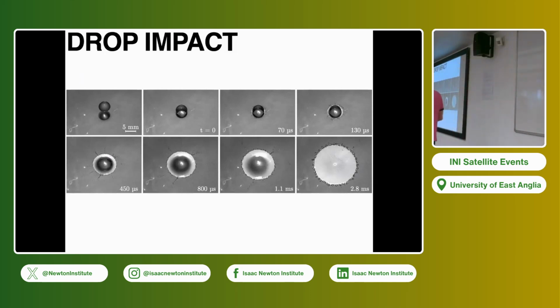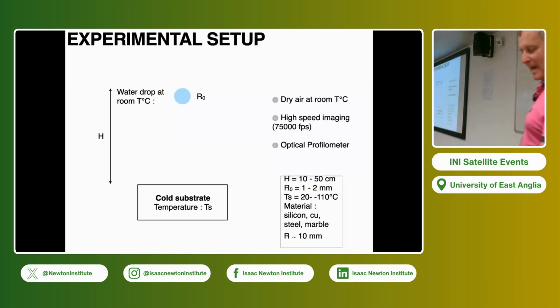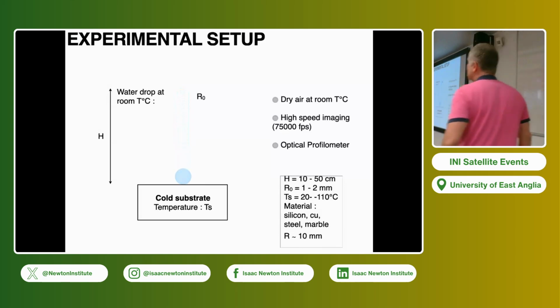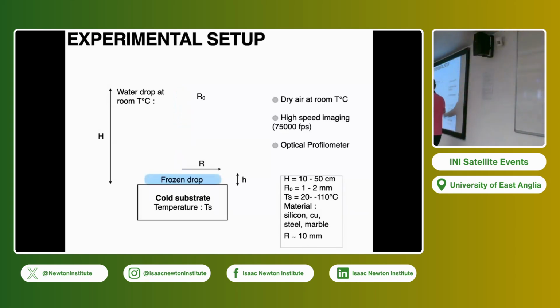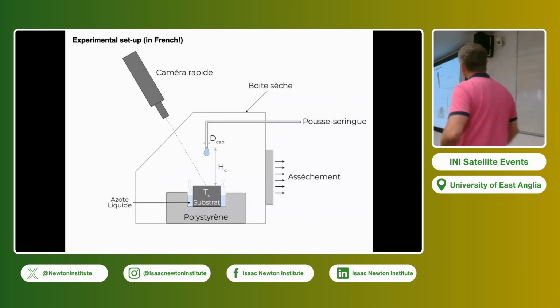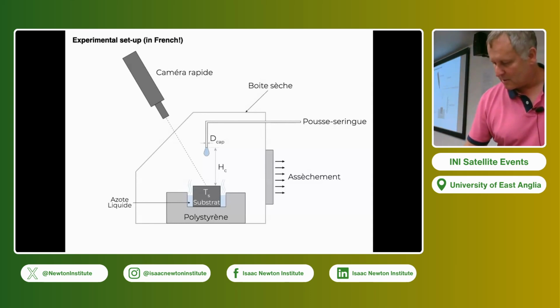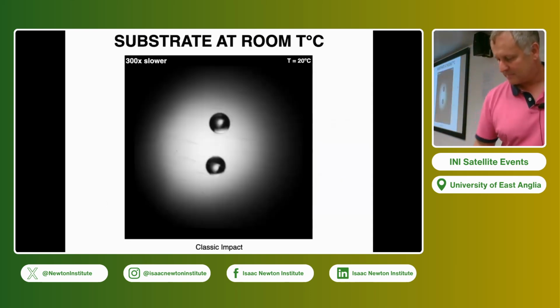So now that we have covered deposition, what about drop impact? Deposition is somehow a specific case of drop impact at zero velocity. What happens when you have drop impact on a cold substrate? Again, we start from experiments. We have a drop of water impacting a cold substrate, and the substrate is below 0 degrees. We expect that at the end of the experiment everything will be solid, but we would like to see how the dynamics work. The experiment was done to control the temperature. We had a big block of metal that we plunged into liquid nitrogen, and we make sure that the temperature is constant during one impact.